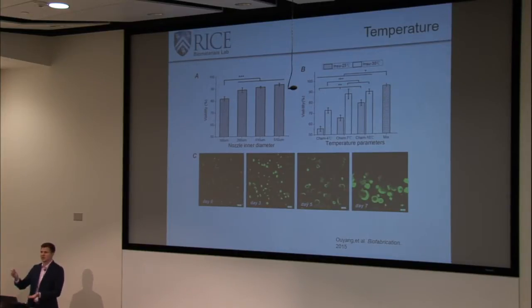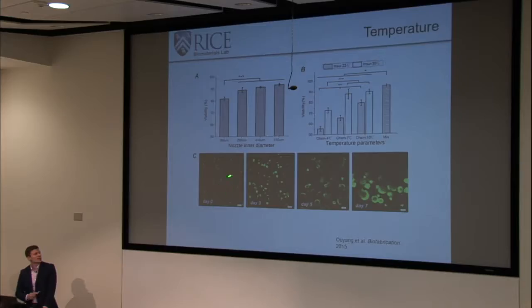So while a material might be liquid at 37°C, when it hits the substrate, you want that material to gel, so you might have cooled down the printing substrate. If you've cooled down this printing substrate to something like 5 degrees or 20 degrees Celsius, then you're going to, of course, affect the viability of cells there. With that being said, we can still print something where cells are printed in a material that's only at 20°C and is printed on a substrate that is at 5 degrees C to encourage gelation.